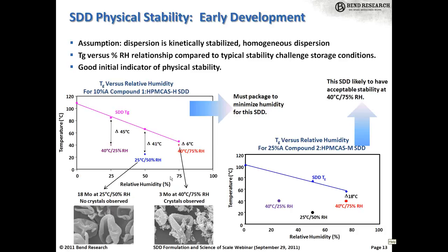And that's exactly what's observed after 3 months. Whereas at other conditions where there's a bigger differential, you're storing it well below the glass transition temperature, and with the lower mobility, you don't see crystallization, which is also observed. So what you would learn from this example is that you're not likely to have good physical stability at this condition, and for this particular SDD you'd have to package away from humidity. In some cases, you can instead formulate around this, but if you wanted to use this SDD for this particular drug, you would have to package against humidity.